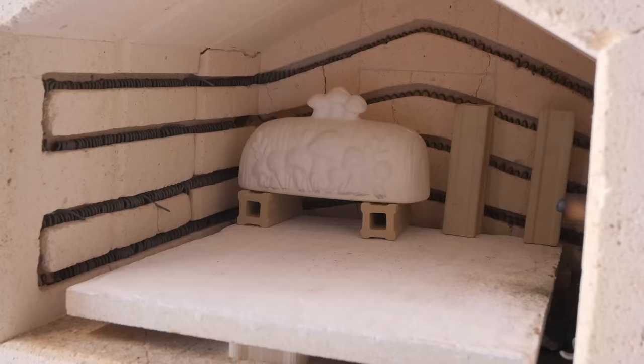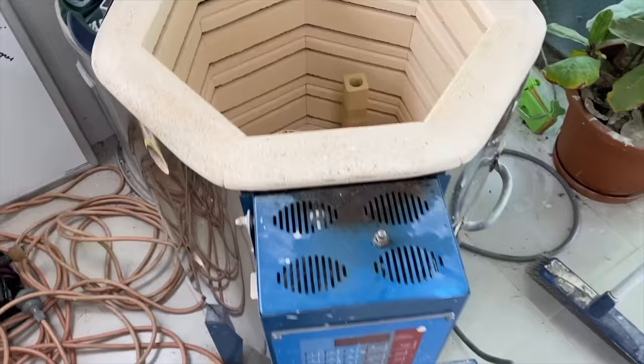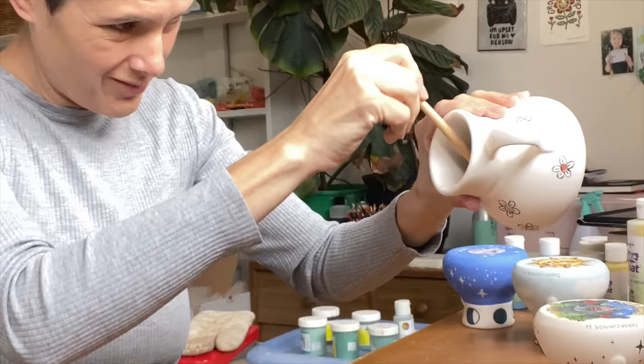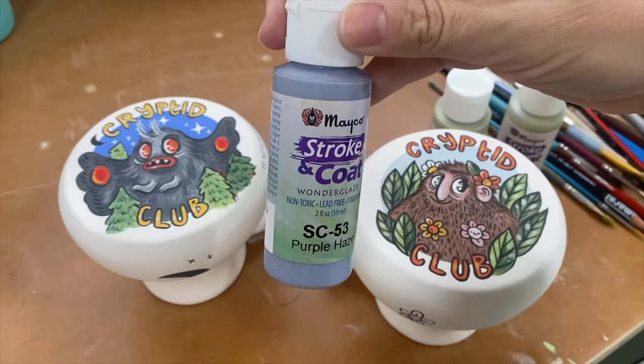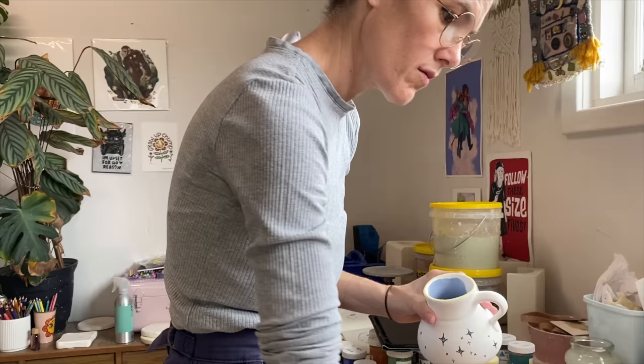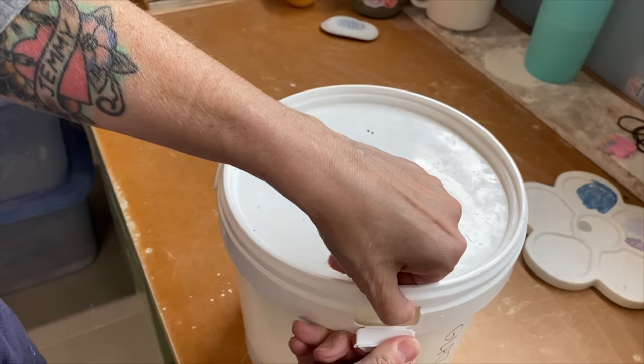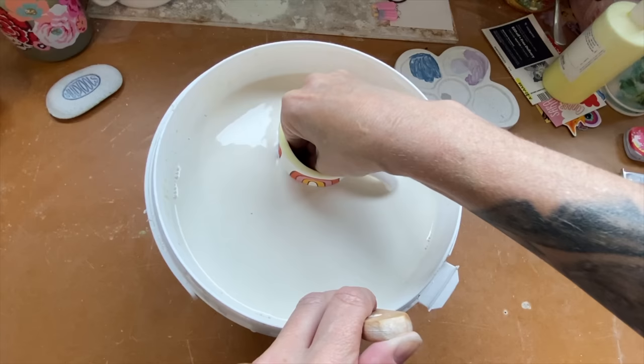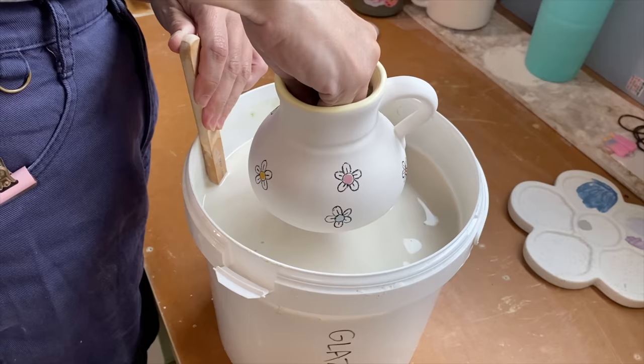Would you be able to share what your thoughts were of your finished pieces? All four came out and I was very happy with them, but two of the actual clay walls were way too thin — unfortunately they're just so delicate that they warped in really strange ways, and one cracked a little bit. I should interject and say that Sarah was a bit of a test dummy for this piece because I hadn't trialled it before sending them to her — I sent her two thin ones and two thicker ones. I think mine also warped a little around the rim and handle because I did a hot fire of my kiln when it wasn't full. I have quite a big kiln — about double the size of yours, Shelby — and it only had these four mugs in there, so the heat wasn't dispersing evenly and it created a lot of hot spots. But considering that, they still turned out really great.